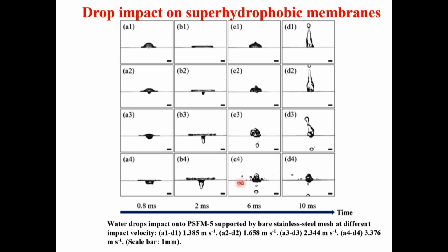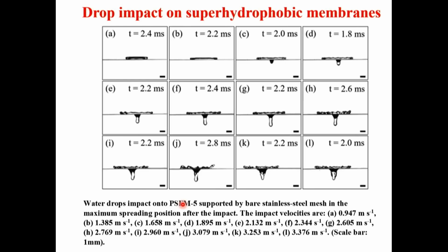Okay, so we are interested in this part below the line. The line itself is a membrane, and below the line is essentially the portion of the water droplet which penetrated through. So now you can manipulate also, like, go to higher velocities and you see even more penetration. The penetration already takes shape of merging tiny jets going through pores, and a central jet appears like that, and more significant portion of the oncoming droplet is perforated, going through the membrane.